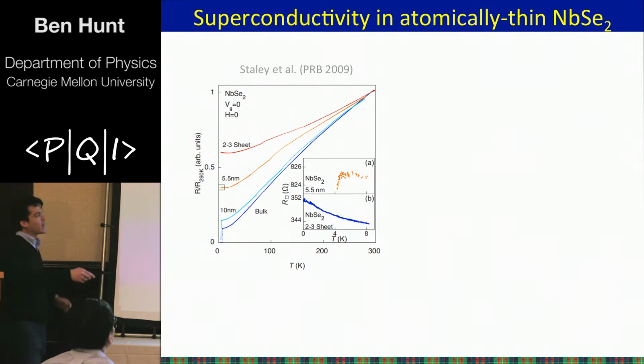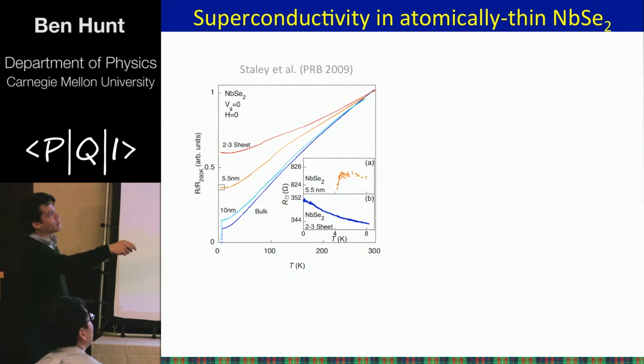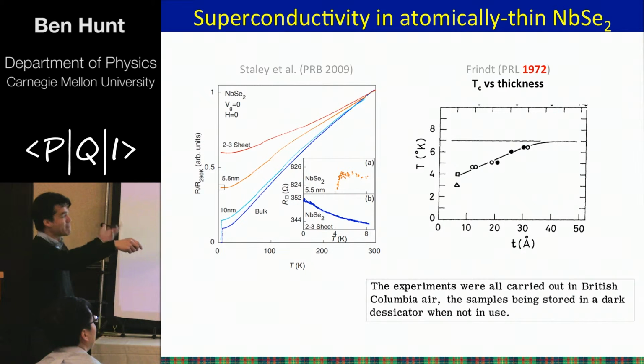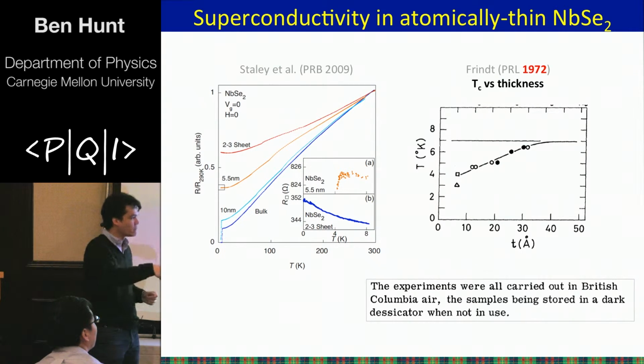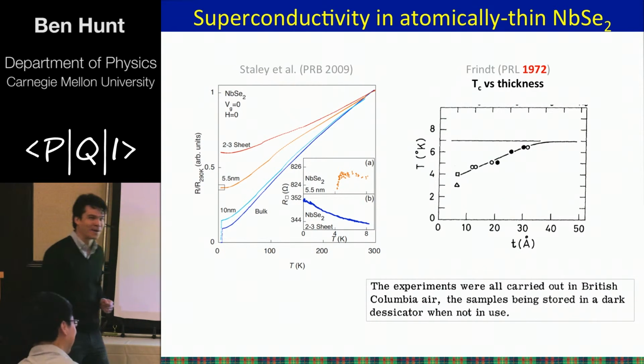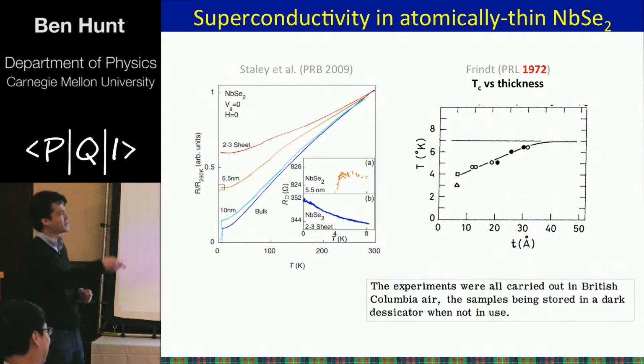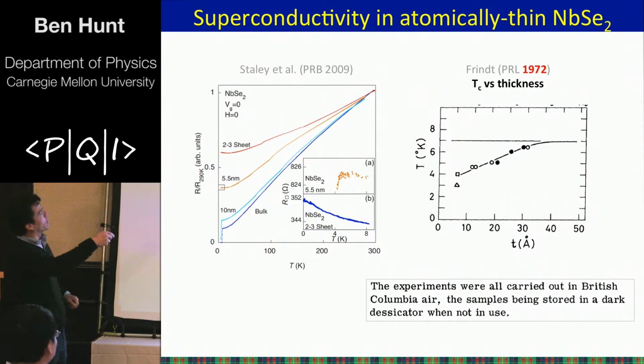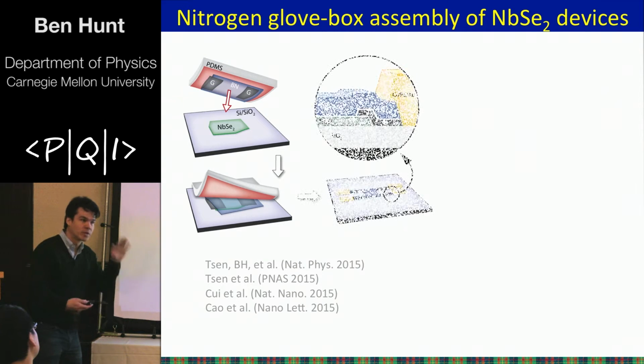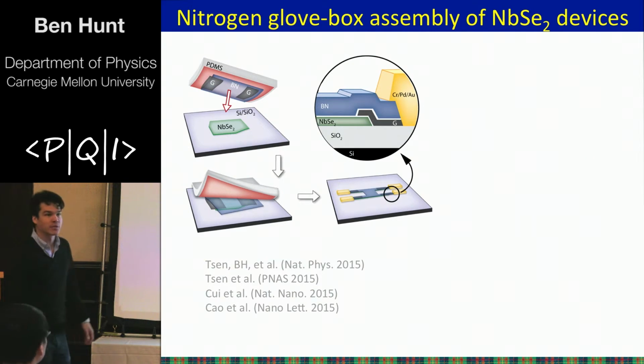Okay? This was a bit of a surprise because well before we started working on it, in 1972, this gentleman, Frindt, studied niobium diselenide. And apparently, he got down to the monolayer limit. So this is a monolayer here, and it apparently worked for him. And the only thing that we could find was that these experiments were all carried out in British Columbia air, which is a very beautiful part of the world, but I'm not sure it's that good. So we had to devise a more kind of brute force way of doing this. So what we ended up doing was taking the niobium diselenide and doing this exfoliation inside of a glove box. So our strategy was to exfoliate in the glove box and then encapsulate it with an insulator, protect it with an insulator, and also simultaneously make contact to it.